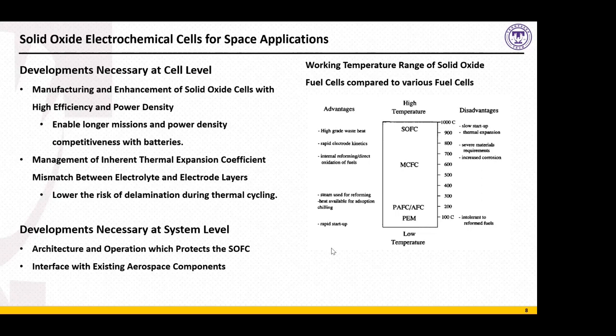You have rapid electrode kinetics, which again is why these fuel cells are resistant to poisoning oftentimes and are quite fuel flexible. The disadvantages of these types of fuel cells is that they have a slow startup time. This is limited by oftentimes the brittleness of the ceramic membranes and the risk of delamination between the layers. So each of the layers will have its own respective thermal expansion coefficient. And if startup is done too quickly, sometimes these layers can delaminate from each other.